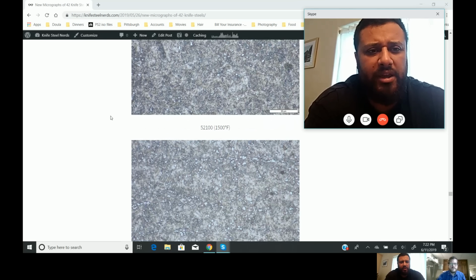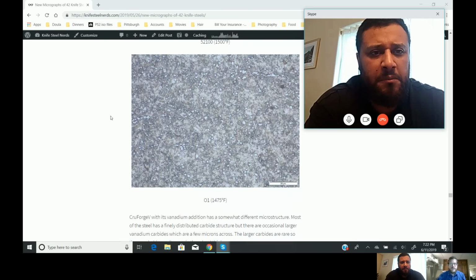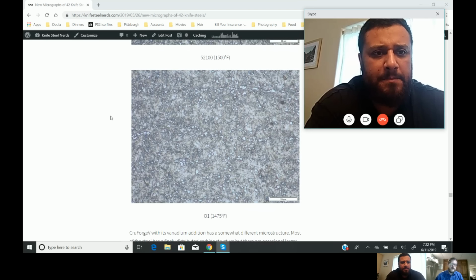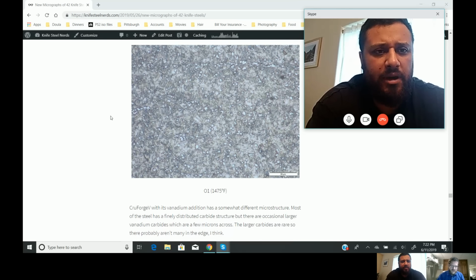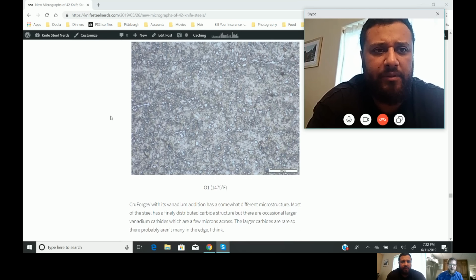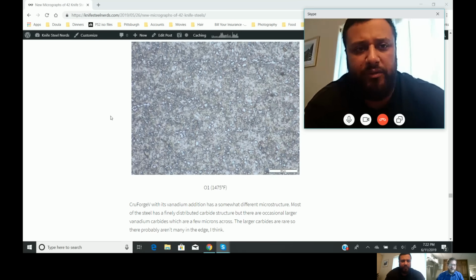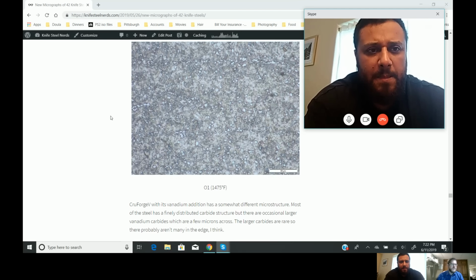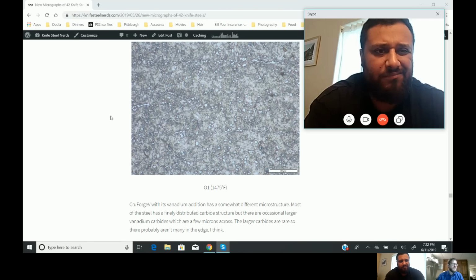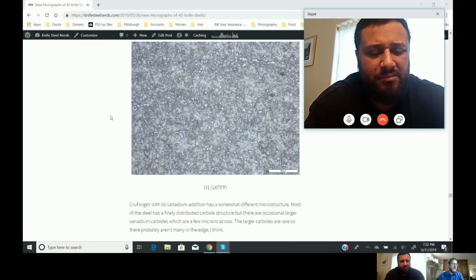What kind of carbide are we getting in the O1? Is that like an M2 or an M6? It's primarily iron carbide. There can be a little bit of the WC tungsten carbide, which is very hard, but it has very little of it. So it's primarily iron carbide. And that WC was a little bit bigger than that VC or NbC, correct? As far as crystal structure? A bigger crystal structure? I don't know. Yeah, I'm not sure. But it has similar hardness to the vanadium carbide.